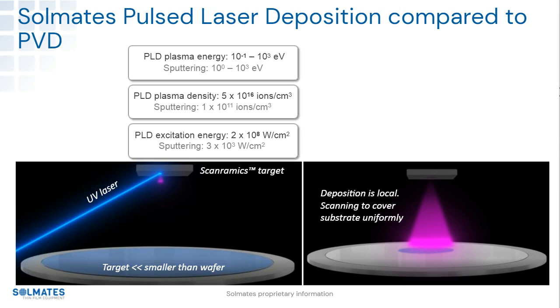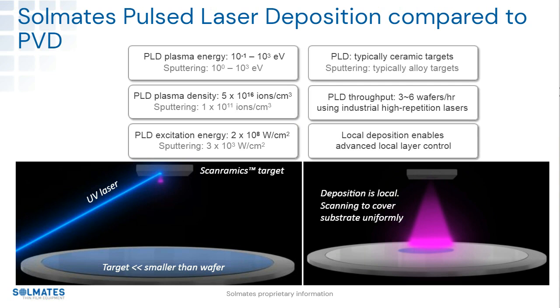That's more than 5 orders higher than in sputtering. And of course, the plasma is very local. It's a bit the size of an apple, but the density is very, very large. In combination with the high excitation energy of these species, this results in a very dense cloud of a supersaturated plasma. And this supersaturation allows for easy nucleation and easy formation of materials, even very complex materials. And not only that, it also allows us to transfer stoichiometric complex materials one-on-one from the target to the substrate. And I think a very interesting part of this is this local nature that allows us to give also local control on the thin film properties across the wafer. And I think this is a unique part in the